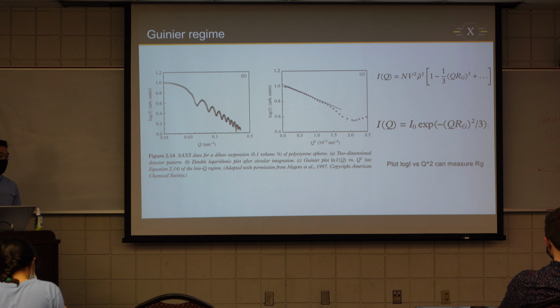So if the particle distance is bigger than that, then that's not a problem. Particle distance, let's say 1 micron versus 2 micron versus 5 micron, none of them will interfere much with the scattering data. But don't over dilute it, because then the sample will be super, super weak in scattering signal.